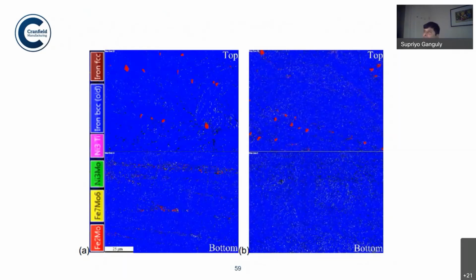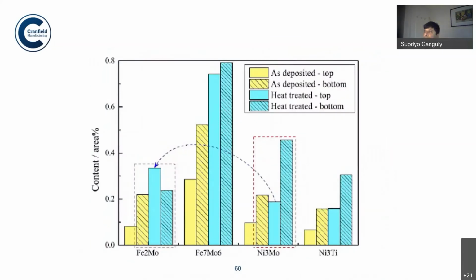Then a study was performed to understand the different proportions of the intermetallic aging precipitates forming in different areas in as deposited and aged conditions. It was shown that the Ni3Mo breaks down and Fe2Mo grows as we do the heat treatment. The different alloy compositions and aging precipitate concentrations were studied and are shown here.